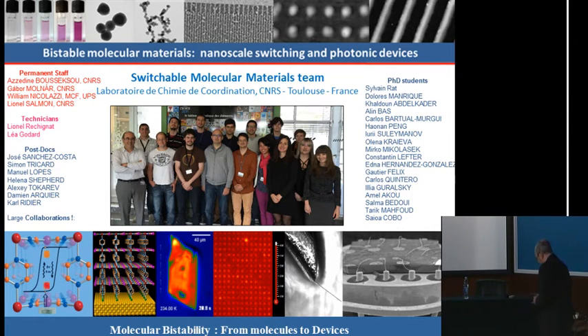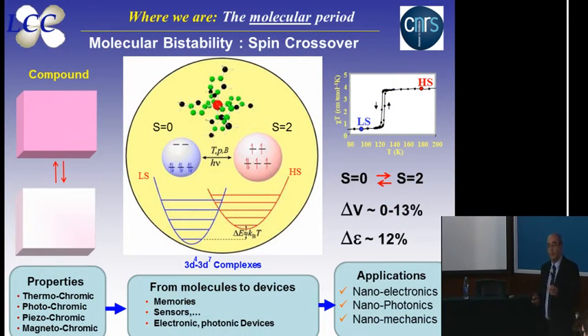So then, as I was telling you, what we want to do is to have molecules, okay? If you look at the energy of these molecules, it's a double well potential, and because the energy gap between the low spin state of the molecule and the high spin one is small enough, it's around kT, that means that you can switch from one state to the other one by application of temperature, pressure, magnetic field, and light. Okay? So then when you go from one state to the other one, because you are switching your electronic properties, you can see a drastic change of the color of the materials. You can go from white to yellow. You can also have, so then, a volume change.